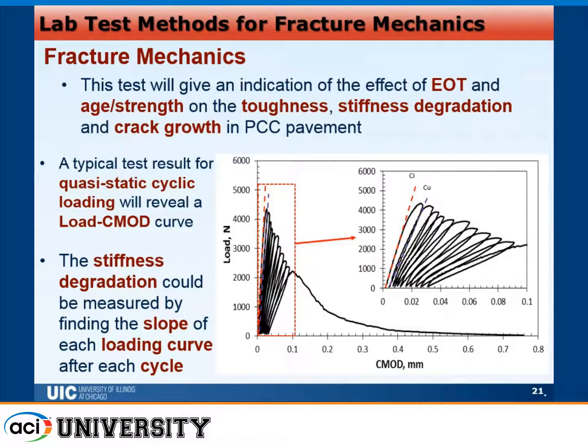The ones with fibers normally take much longer, because without fibers the sample will split in half at around 1 millimeter, which is 0.04 inches, but the ones with fibers take up to 1 hour of loading, and sometimes 1 hour and a half, because the rate of loading is too slow.